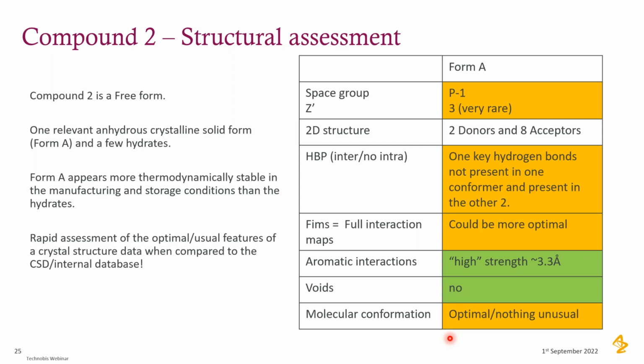But when we review the crystal structure features and we risk assess those in terms of space group, Z prime, H-bond propensity, full interaction maps, aromatics, voids, and molecular conformation, you can see there's a lot of flags coming out. That highlights some kind of risk, especially around the Z prime equal 3, when you have 3 molecular conformations in the unit cell, which is pretty rare for what we call a thermodynamically stable form. But that doesn't mean it's not possible. It's just for us to keep an eye on, okay, maybe we need to do a bit more work to confirm that and to give more reassurance.